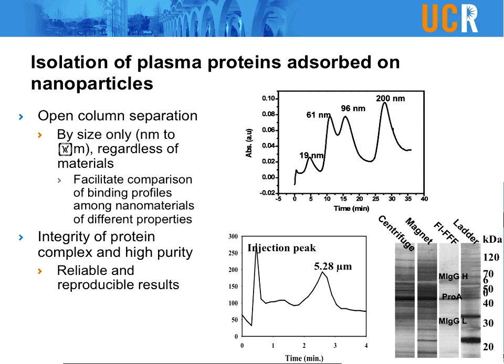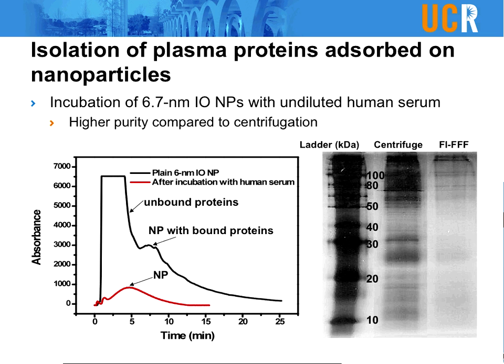However, one injection in the flow system will clean up most of the non-specific protein, and then the specific protein will show up very clearly on the gel. So therefore, we can apply this technique to analyze what plasma protein can bind to the nanoparticle very strongly. So we incubate the nanoparticle with plasma proteins for 4 hours, and then we inject the nanoparticle incubation solution into the flow system, and then you could see a